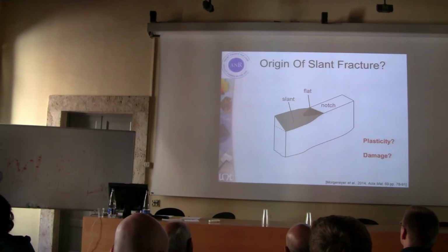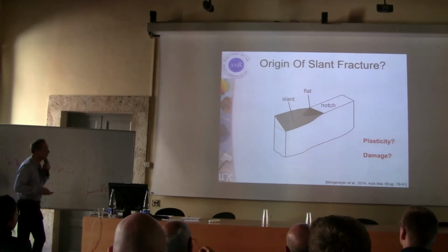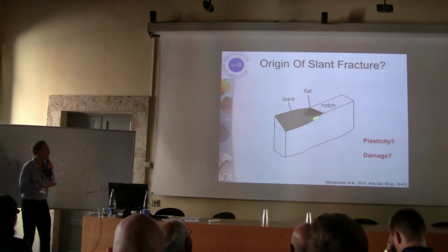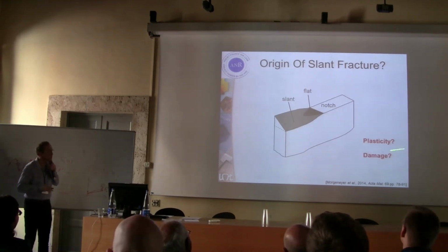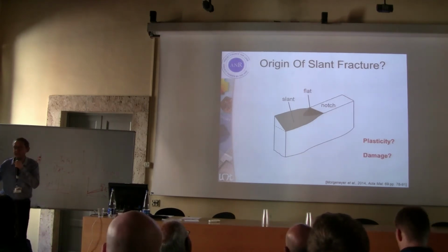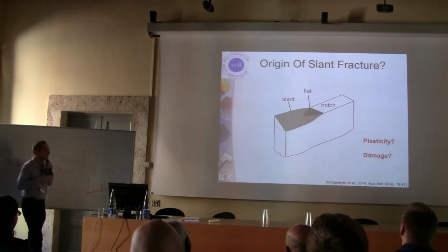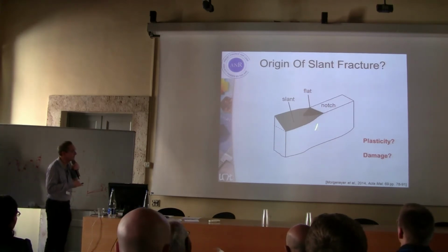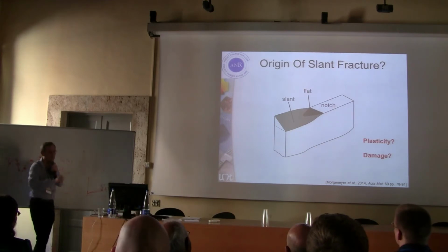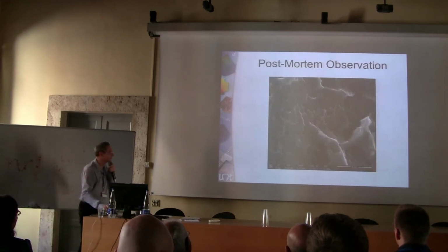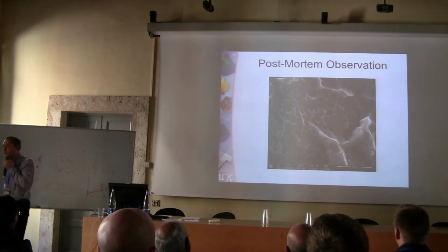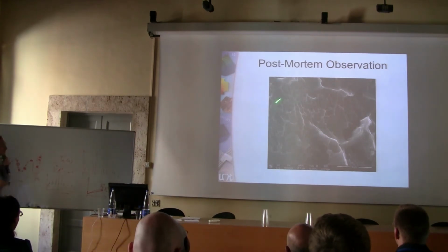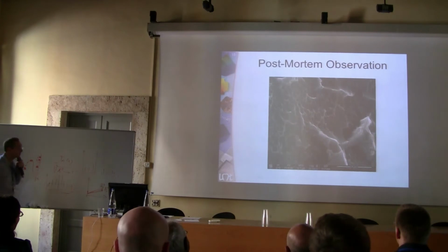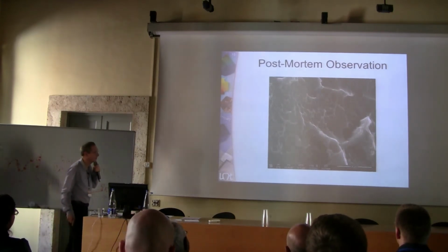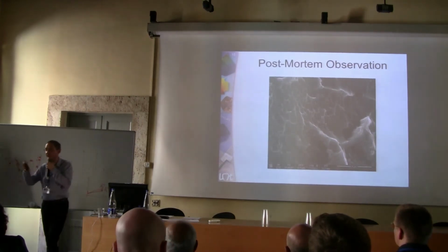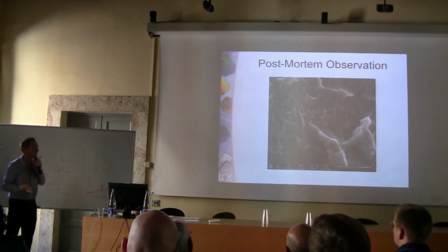There are basically two explanations: one, plasticity occurs first and drives this transition, or it's damage. In damage, of course, you would think in terms of localization, and the fact that eventually you may have a localized band. Now, if you look at post-mortem observations of such materials, what you see are typical signs of ductile damage, dimples all over the place. So in that sense it's pretty clear you have a damage mechanism, and it's the driver.